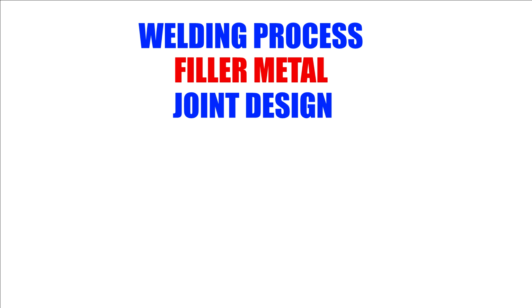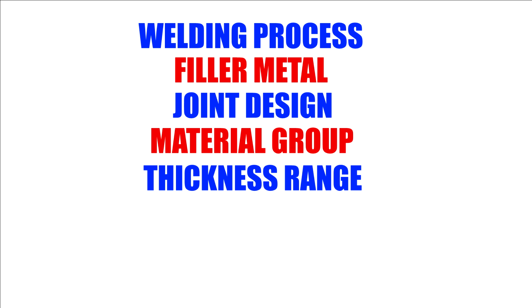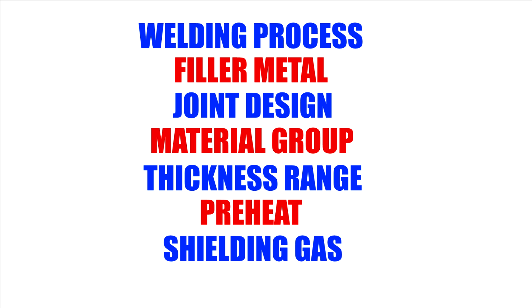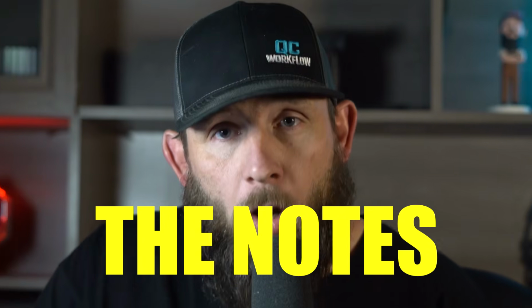So here's the big takeaway. Don't just glance at the welding procedure and move on. You want to check the process, the filler metal, joint design, material group, thickness range, preheat, shielding gas, parameters, and always read the notes. A lot of issues happen because somebody only looked at the top half of the procedure and missed a restriction that was buried lower down. Once you understand how to read a procedure, they become a whole lot less intimidating, and all it is is a roadmap for how that weld is supposed to be made.